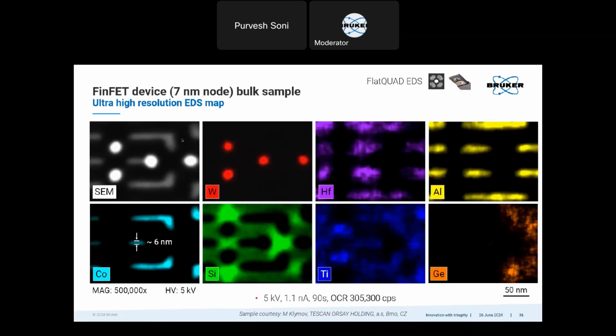And this is a bulk FinFET semiconductor sample, and it was measured at 5 kV and probe current of 1.1 nanoampere. And we can see the very high count rate of 305,000 counts per second. And because of this very high count rate, I only had to measure for 90 seconds, and I could get a very good statistics map. And I could even resolve a feature which was around 6 nanometer in size.